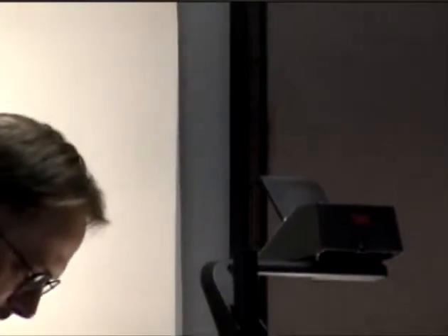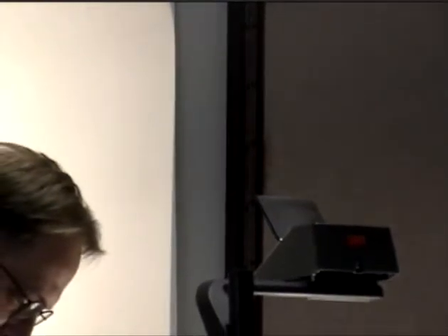If reaction rate is governing the reaction of the primary particle with the aggregate, you get denser structures. If transport is limiting and it reacts immediately, you get lower dimension objects. All right, and that business has been well worked out.